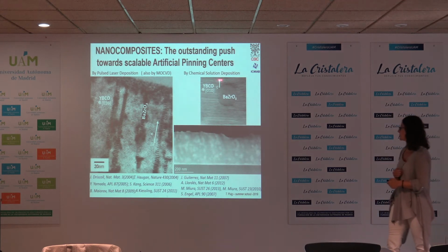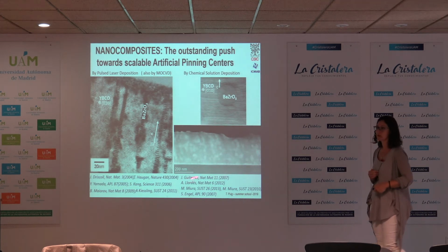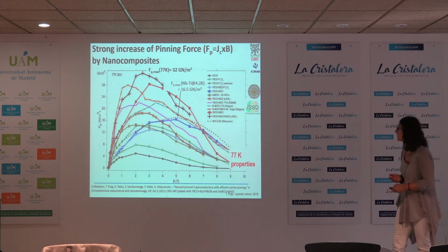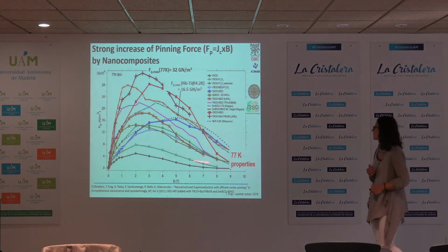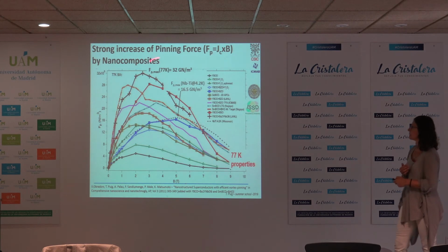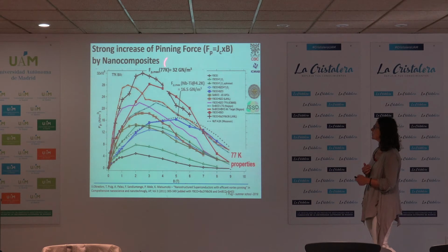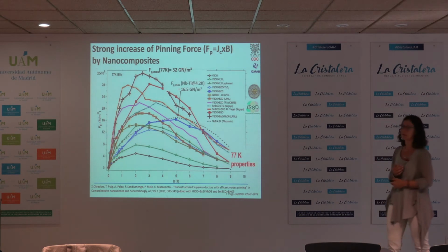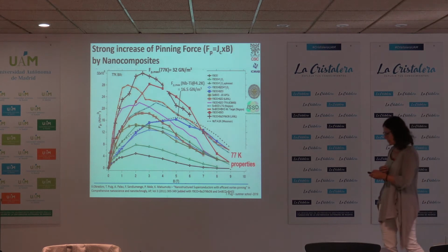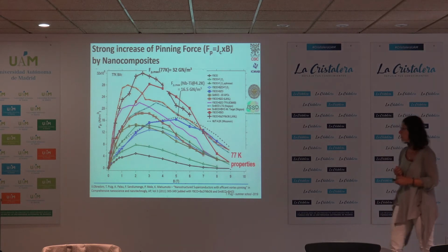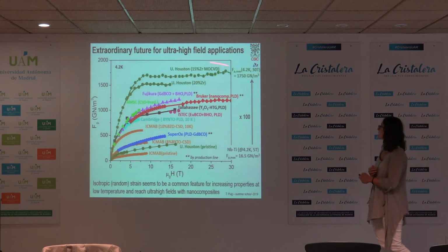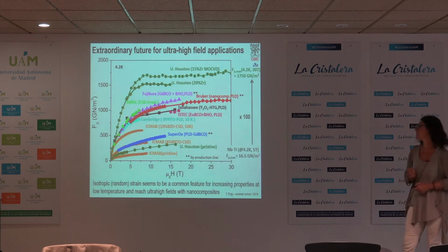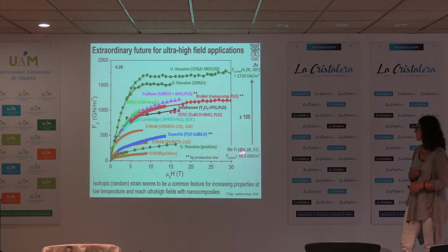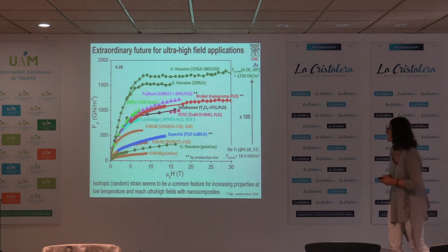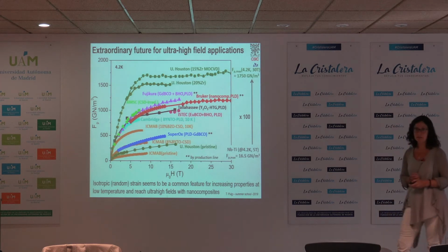In the case of chemical solution deposition, we have been able to put nanoparticles into the material, which are also good pinning centers. In fact, if we look at the pinning force of these nanocomposites, we see that from the pristine values we can really go to very high values of pinning force, which in fact at 77 K are able to double the pinning force value that you have in niobium-titanium at 4.2 Kelvin. And these are different ways of producing these nanocomposites. If you go to 4.2 Kelvin, you can even get pinning forces which go beyond 1.7 teranewtons per cubic meter, which is more than 100 times what you get at 4.2 Kelvin for niobium-titanium. So clearly there's a lot of interest in these materials at high temperature but also at low temperature.